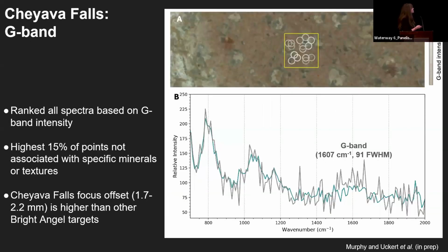So we did the same thing on that natural surface of Cheyava Falls, but this time we ranked the spectra based on the most intense G bands. And what we found was there doesn't appear to be really any change in the mineralogy with these higher G bands or the more intense G bands. And it's just kind of scattered throughout the matrix. But this was quite a bit out of focus or away from our ideal focus. We were a bit too close to the targets. That's why the spectra is pretty noisy here. So there could be some sort of association with texture that we just couldn't pick up because we were a bit out of focus.